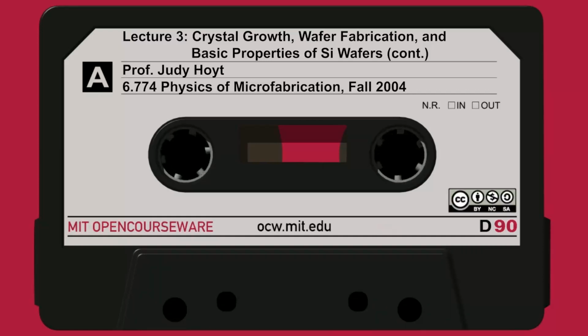It turns out that no one's ever really measured exactly the equilibrium concentration of V and I by any direct process, particularly at the silicon process temperatures. The truth is the concentration is so small compared to physically reasonable macroscopic numbers, like the number of silicon atoms, 5 times 10 to the 22. We're going to see that vacancy concentrations are in the 10 to the 12th range, 1 part in 10 to the 10, much, much lower. And so it's just very hard to measure them directly. But people have estimated them.